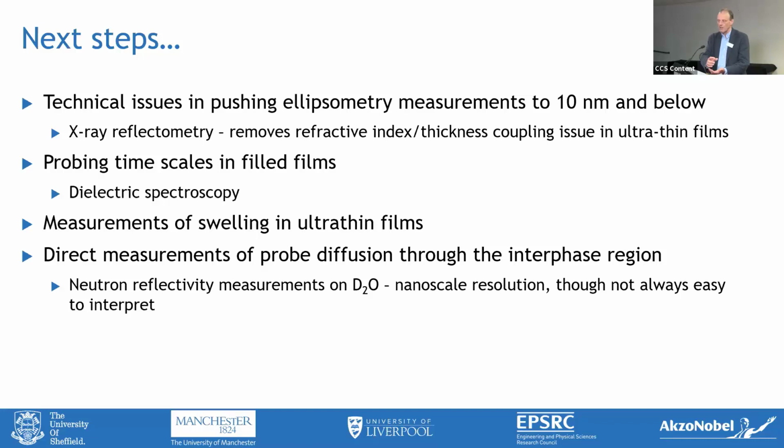That's a very small scale interaction, but the argument we're making here is that it then gets turned into a longer scale effect that penetrates up through nanometers. To explain that, we have to invoke the ideas about cooperativity that people have in theories of the glass transition. But yes, I think it could be either way.